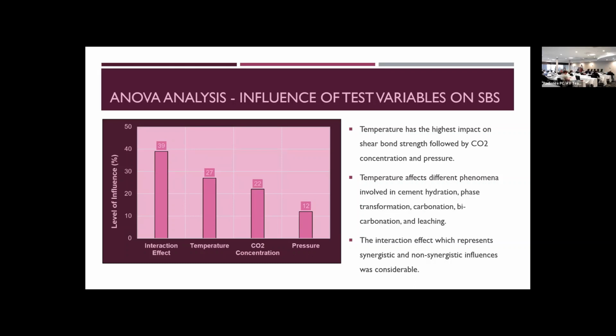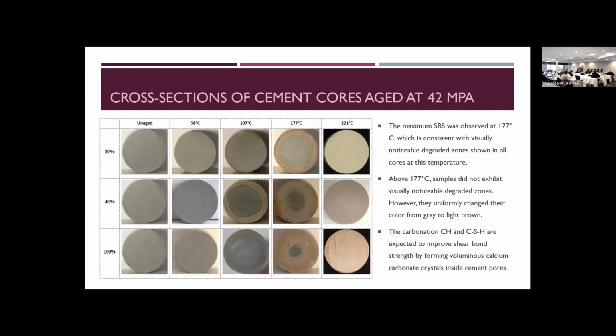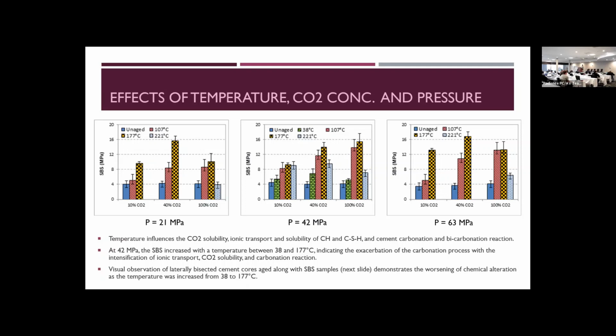No, this is a parametric test. So we didn't perform a non-parametric test here. We are very much aware of the fact that the size of the sample will definitively affect the results, especially if we want to upscale them to the real world. But the project, the way we started, was in particular to be able to do some comparison. And that's why we believe that although the size of the sample is small and may not be fully replicated for real situations, at least the tests that we have done here, and you can easily follow, for example, in such a graph, show a very important tendency of the bonding evolution with pressure and temperature.